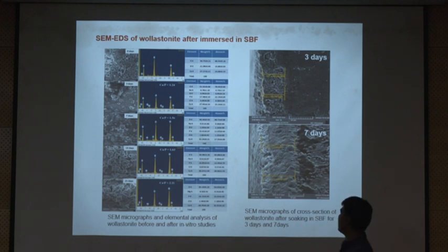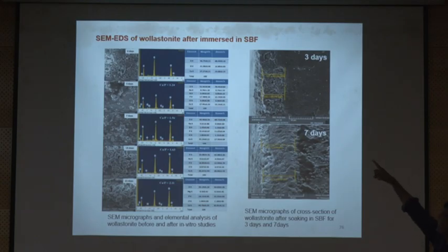So this is a micrograph, the cross-sectional view after soaking 3 and 7 days. It is increasing from 49 micrometer to 120, 140, 150 micrometer. I am talking about the thickness of the layer. It means the material is bioactive in nature. So the activity is more here.